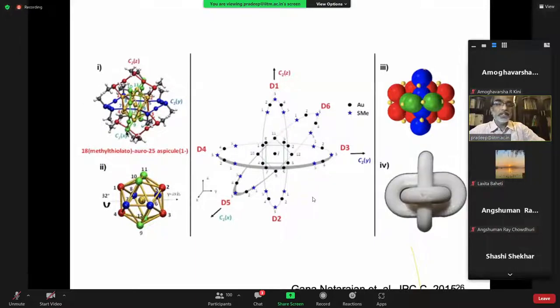If you look at this cluster system, there are three rings. There is an icosahedral 13-atom core, and then there is a ring, which is red, and then a blue ring, and then a green ring. All of them are perpendicular to each other, with small changes. Using this kind of ring structure, we created this nomenclature system starting from a central atom. You have 12 atoms surrounding this, and so we can label these atoms just as labeled here.